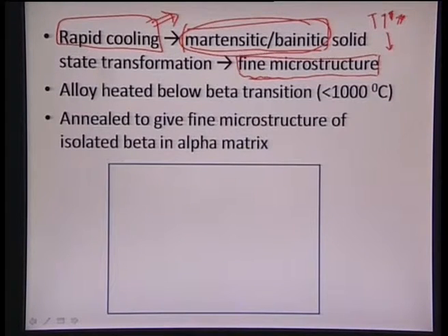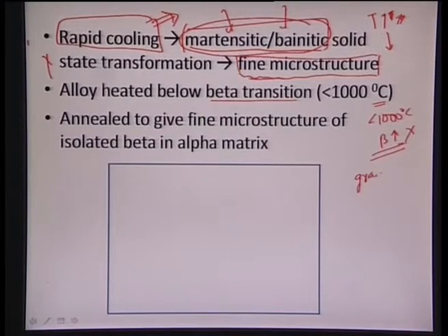And again, the alloy is heated or cooled below the beta transition. So we are not letting this material go above 1000 degrees centigrade. We are letting this transition happen below 1000 degrees centigrade. So we are heating the material to less than 1000 degrees centigrade, and we don't allow the beta to form completely. Once beta is not formed completely, rapid cooling can induce martensitic or bainitic-type transformation, and at the same time we are not allowing the grains to get coarsened. So grains remain fine and they are retained as such, because we are heating them much below 1000 degrees centigrade, and then they are basically annealed to give a very fine microstructure.